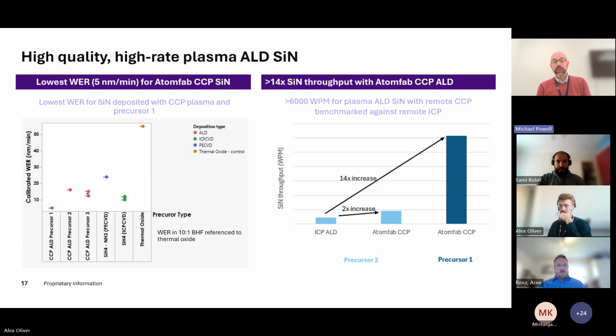But we are able to do about a 14 times increase on our standard ICP ALD. And this is bringing silicon nitride into the ability to have a high volume manufacturing ALD route for silicon nitride. We've modeled this on a 20 nanometer film, and we can do over 6,000 wafers a month if we do a 20 nanometer film of silicon nitride.